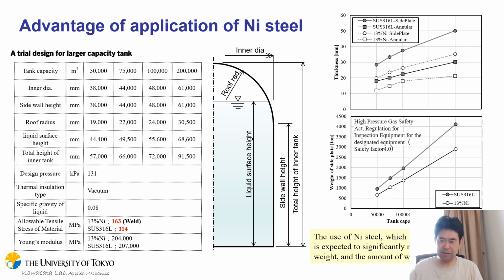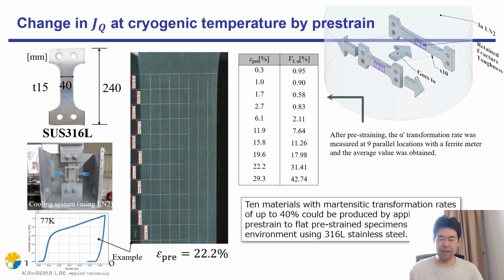Now the first target is 50,000, but in future the size has to be larger. So in the case of 200,000 cubic meter, with stainless steel, the thickness of the side wall would be too thick. So much higher strength, much higher yield strength steel or material should be used. In that case, this is one candidate, 13% nickel. So this is the next topic.